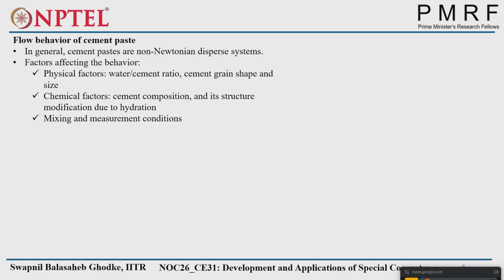Similarly, cement grain shape and size. The finer the material, the higher the hydration will be. Irreversible breakdown will be possible, so very fast setting will happen. That's why yield stress will increase and plastic viscosity will also increase. Cement grain shape depends on whether the particles are spherical or cubical. And chemical factors, the composition of cement, like faster setting cement or any other type of cements, sulfate resisting cement. Based on that, chemical factors also affect the rheological parameters. Then hydration is one of the mechanisms which is irreversible. And then mixing and measurement conditions.